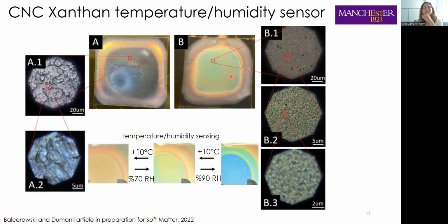It is not as iridescent as before because the xanthan itself doesn't form photonic phases. It is going in between the photonic structures. So the discontinuity and the thin layers between these compartmentalized units is giving us scattering, but it has still very good color response.